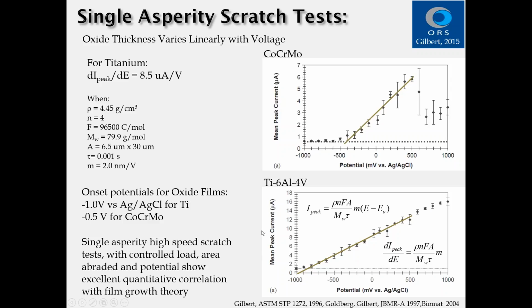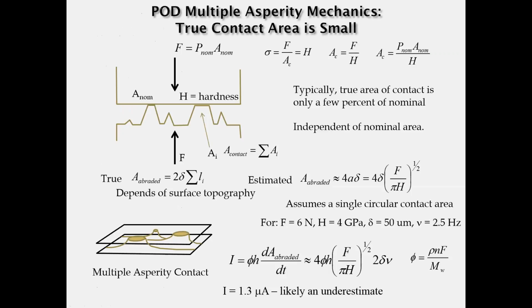So a very good fit between the theory of high field growth and the measured behavior in a single asperity scratch test. The onset potential for titanium is down here at -1 volt. The onset potential for cobalt chromium abrasion is at -500 millivolts. And so those are the important parameters that come out from these tests.